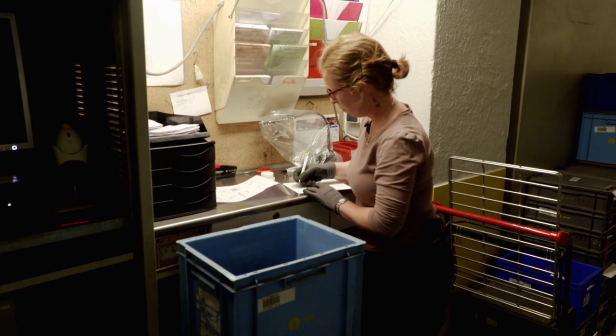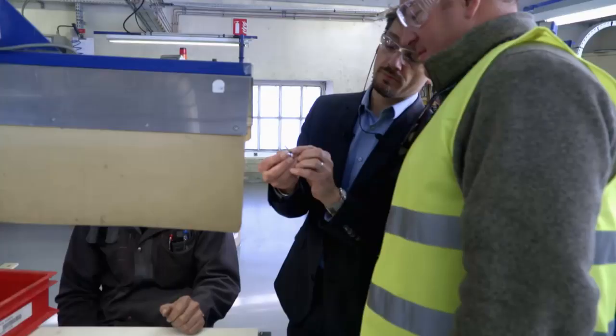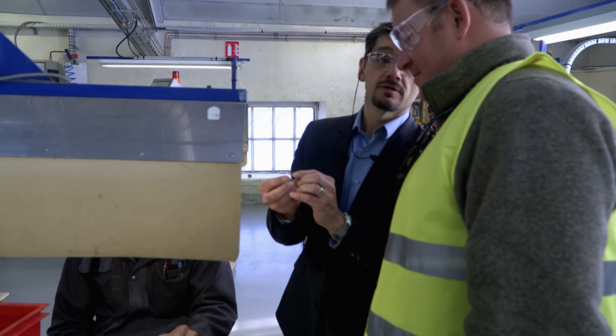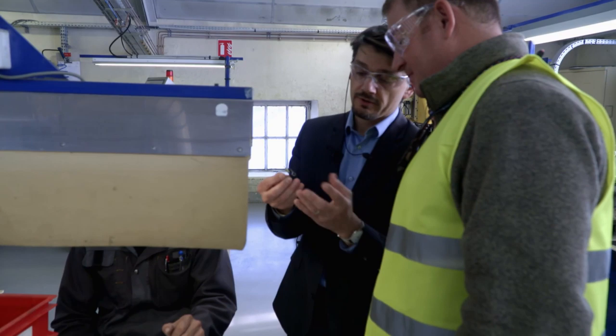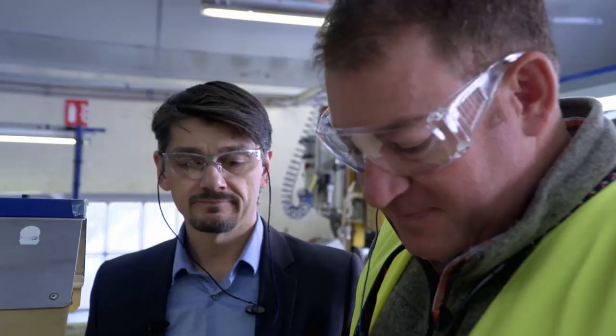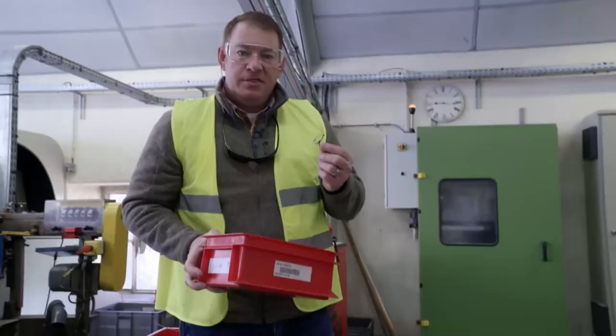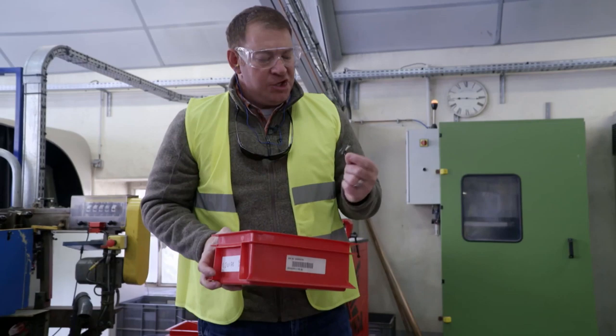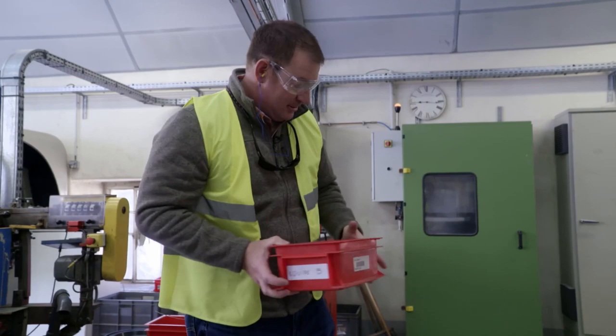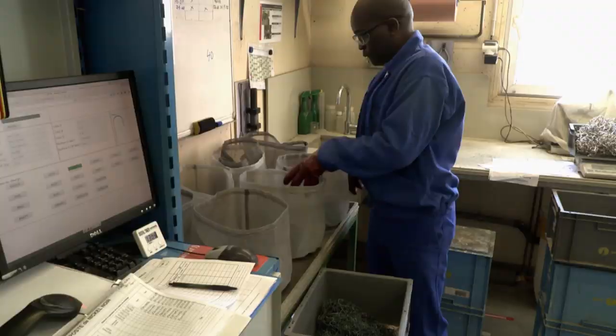These hooks are now tempered — look at that, they bend before they break. They're perfect. Severine Claude checks a bunch of the tempered hooks to make sure each bends just enough before it breaks. We prefer to destroy a hundred hooks out of a batch and make sure the batch is fine rather than having to dump millions of them. She tests sharpness too. The team also looks at fit and finish — if the brazing area isn't perfect, it all goes out to be recycled. Those that pass sit ready for the prettiest part of the hook-building process — up next, hooks go for a swim.